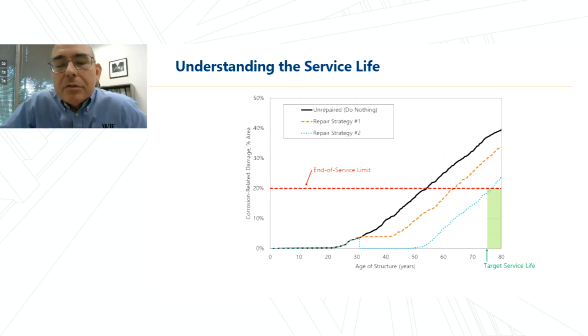Now we consider repair strategy number 2 that's also implemented at about 30 years. It's shown by the blue dotted line on this graph, and it does achieve the target service life. In this case, repair strategy number 2 attempts to reverse or undo the damage that was present in the structure at the 30-year mark. And that's visible based on the downward vertical portion of the blue curve at the 30-year mark when the repairs are installed.